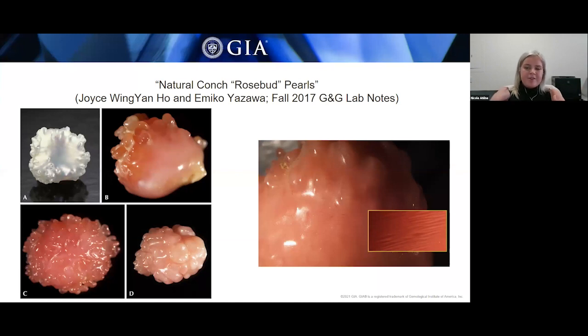And the photomicrograph that you can see on the right depicts the characteristic flame structure that was seen in at least one spot on every pearl. And so Raman spectra of the pearls did show aragonite and natural pigment peaks as expected from pearls from the Strombus gigas mollusk.